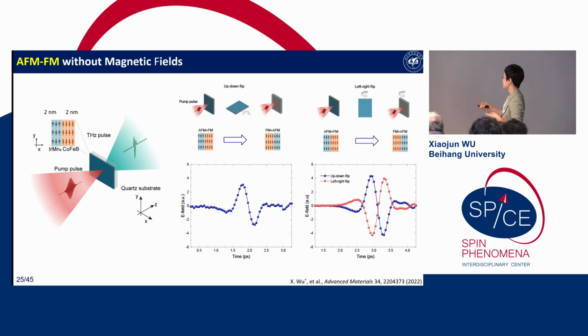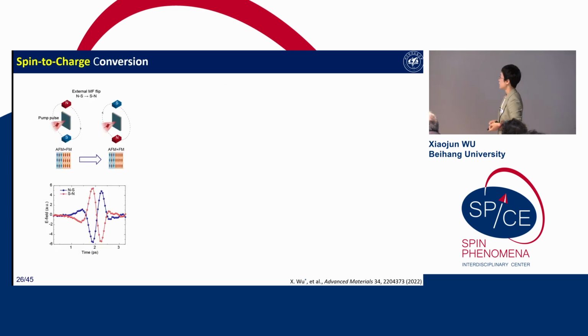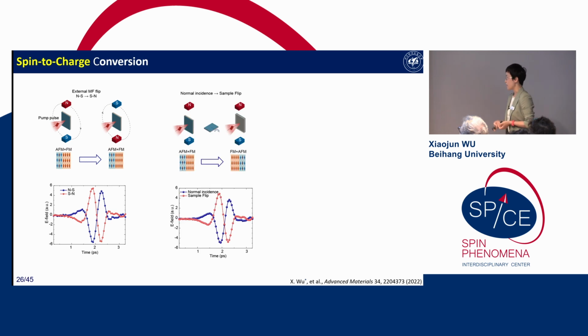So the terahertz phase will change. That is a very easy way to check this spin pinning effect. And other things that we try to further confirm the mechanism, we add an external magnetic field. The interesting thing is that if we add an external magnetic field here, the spintronic emitter becomes a conventional spintronic emitter, like platinum, cobalt iron boron, and then we check it. We just change the magnetic field direction, and then the terahertz radiation phase changes.